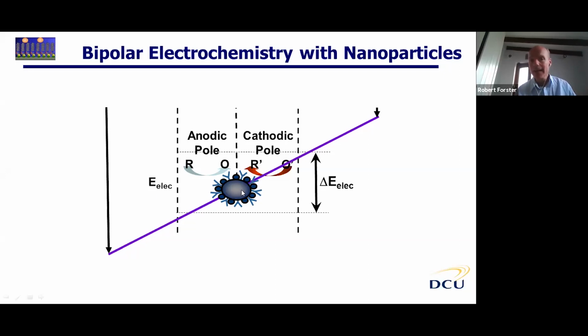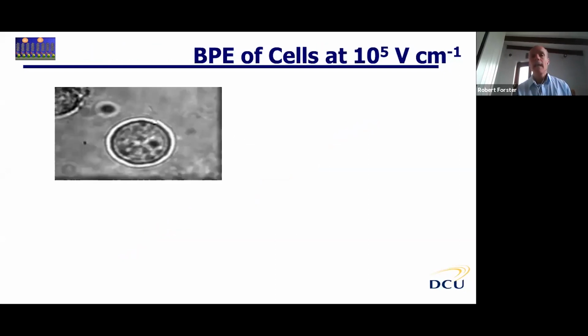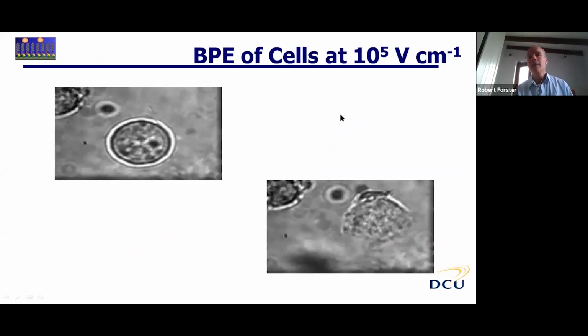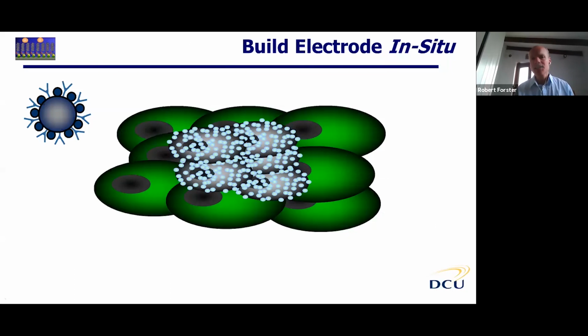But if we want to go to the nanoscale, we want to use gold nanoparticles decorated with antibodies so we can target them, and decorated with ruthenium dyes so we can do this ECL emission. Now, if this is 100 nanometers, we're going to need 10 to the 5 volts per centimeter electric field strength. And of course, as everyone in this audience knows, if you expose cells to a 10 to the 5 volts per centimeter electric field, what happens is they burst, they lyse, they disrupt. So we're interested in developing strategies to get around this, to exploit the power of wireless electrochemistry.